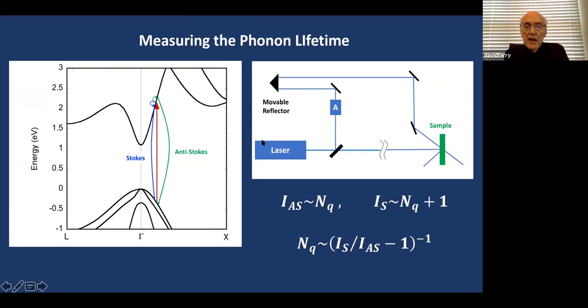This is one way. Have a laser. We used 1.96 eV in that last example I said. We use a beam splitter, so most of the signal goes through, a powerful pulse hits the sample. A small fraction is taken off, maybe amplified if it's too small, goes through a movable reflector so you can slow it down and delay it relative to the first pulse, bring it back and run it through the sample and do Raman scattering with this probe pulse.